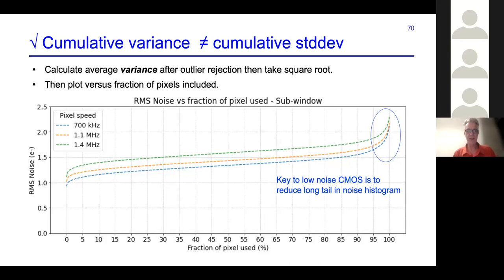And so this is an RMS noise curve, which is essentially a cumulative distribution, except it's been turned around so that the axes have been swapped. So it shows the RMS noise for a given pixel fraction used. So if you use 99% of the pixels, you get 2 electron noise. If you use 100% of the pixels, you get about 2.3. So the noise is not too bad, and there are many, many pixels which are much quieter.